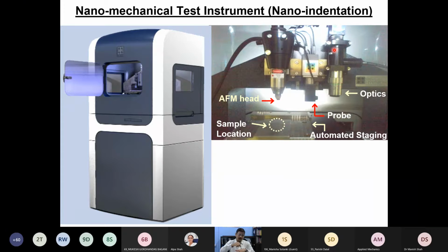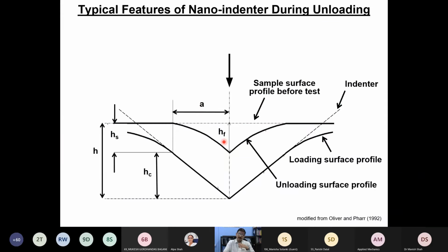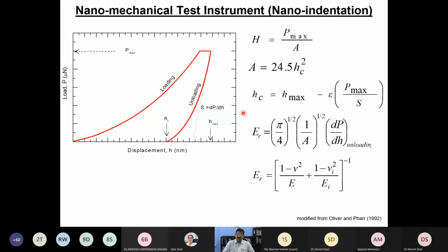That means you poke the surface of the polymer using the diamond tip, making a depth of indentation in the range of nanometers, at most micrometers, and the amount of load applied is in the range of micronewtons, not more than that. How do we do that? This is the surface profile of a nano indenter; this particular technique was proposed by Oliver and Pharr in 1992. This is the initial surface. After indentation, the surface may get deformed like this, and by plotting the depth of indentation versus the load applied, you can really measure some of the mechanical properties of a polymer.